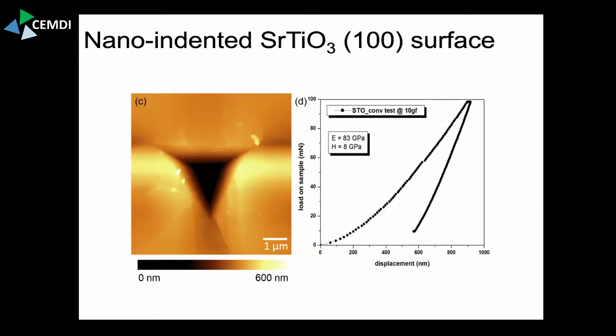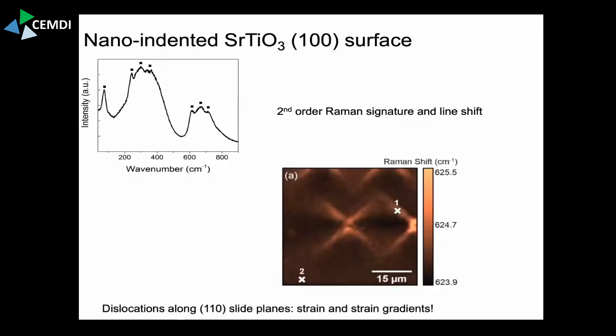So if this material was rubber or some kind of jelly, you would expect a triangular strain field, because that would be the symmetry. What we rather measured when we did a Raman scan, using a technique of Raman spectroscopy to measure strain, was that you get these wing structures. In the middle would be the indentation, and you get these fourfold symmetries.